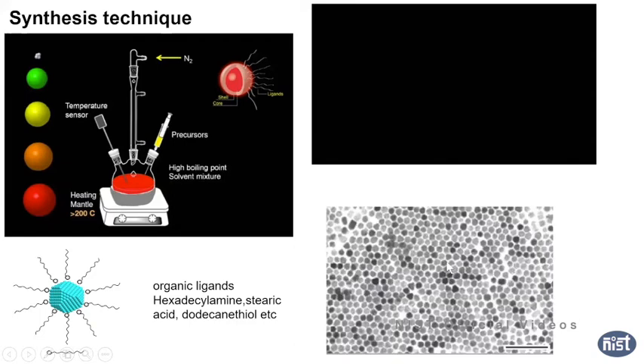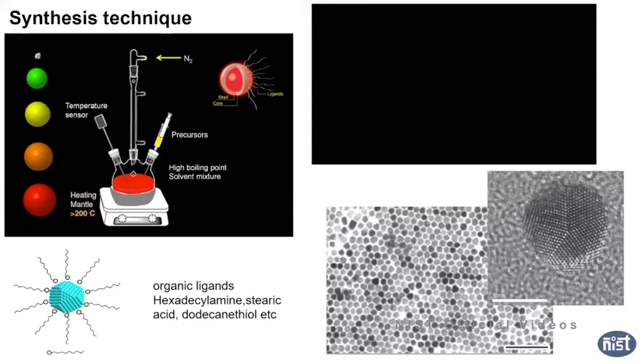And you can see, as I told earlier, you can have very homogeneous nanoparticles and nanocrystals. You can see all the nanocrystals look the same, almost 8 to 9 nanometers, 10 nanometers, something like that. So this is the best way to make colloidal nanocrystals, and that's why we say colloidal quantum dots, because they are dispersed in the solvent and behave like a colloid. And you can see how crystalline it is.